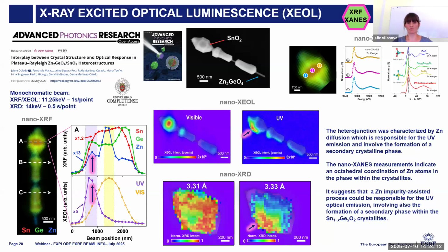Because thanks to all those results of fluorescence, diffraction, XEOL, and XANES, all this suggests that the zinc impurity-assisted process is responsible for the UV optical emission, which in fact involves secondary phases in the tin germanium oxide crystallite that we have in this heterostructure.